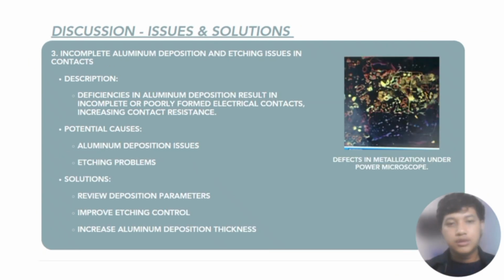Our third issue is the incomplete aluminum deposition and etching issue in the contact. Basically, like in the image, there are a few defects in the metallization. This problem will cause incomplete aluminum deposition and give us a less precise value in the IV characteristic graph. We can solve it by reviewing the deposition parameters again or improving the etching control so it will not undergo over-etch or under-etch.